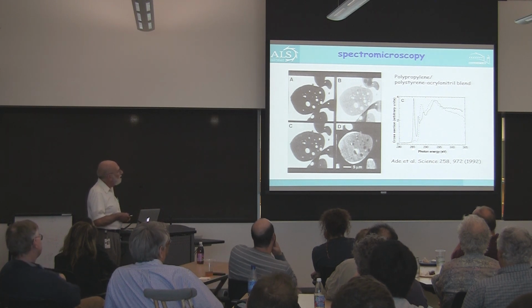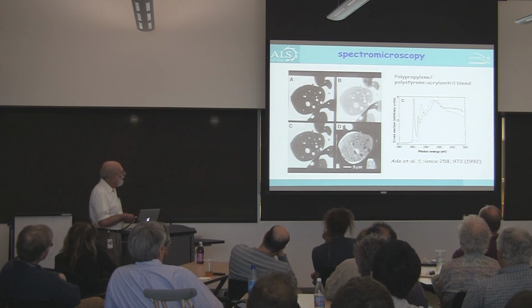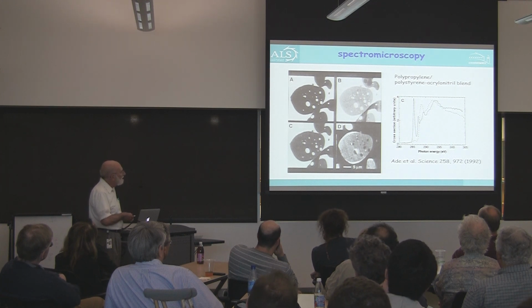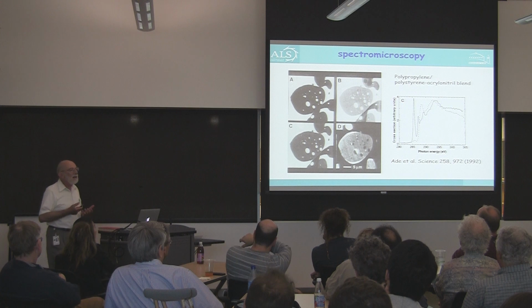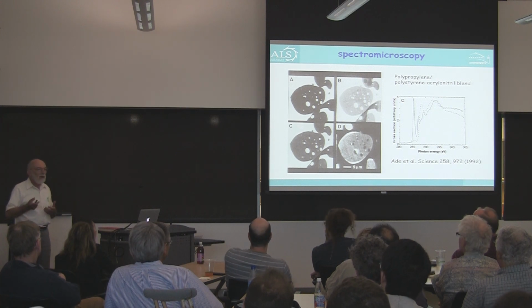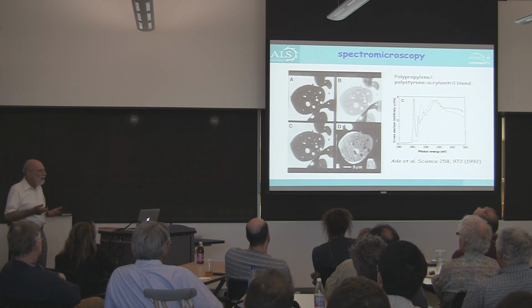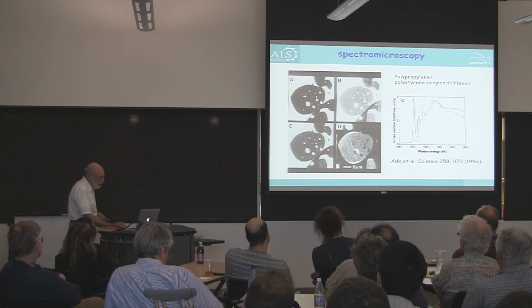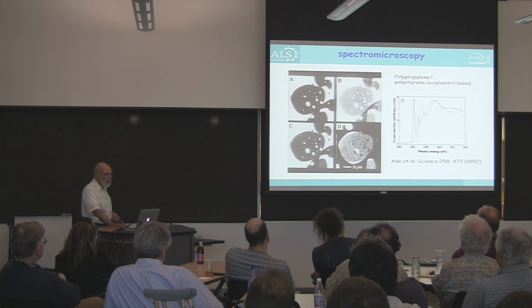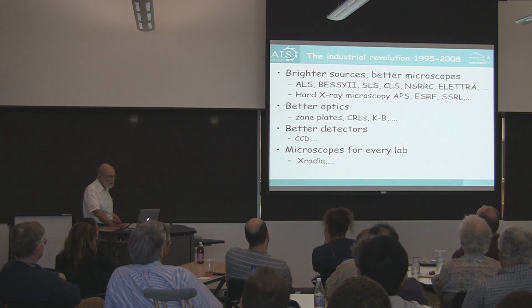So by going to image at 285 eV, where the copolymer had a large peak, we got an image like this, while when we went to 288 eV, where polypropylene absorbs more, we got an image like this. So it was very clear that combining X-ray microscopy with X-ray spectroscopy is a very powerful tool to develop. And of course, that has been a major use of X-ray microscopy ever since.